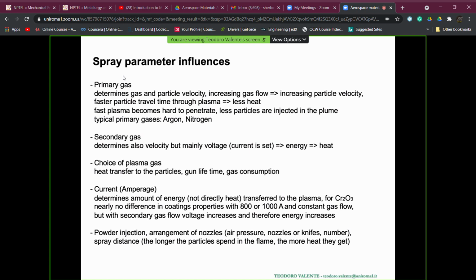as well as also the gas consumption, that's an economic issue, as well as the gun lifetime for the electrodes consuming. The current, when we are going to work with setting the current, not the voltage, also determines the amount of energy which is transferred to the plasma plume. Let me say that it depends on the materials, but just to give you an example, there is not so much difference if we are going to spray one special material, that is chromium oxide, in coating properties, if we are going to use values of current imposed in the range 800 to 1000 ampere with a constant gas